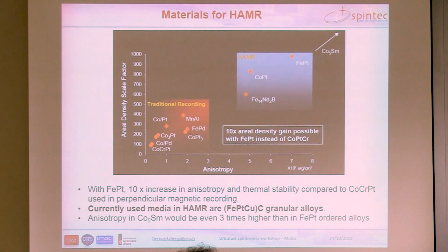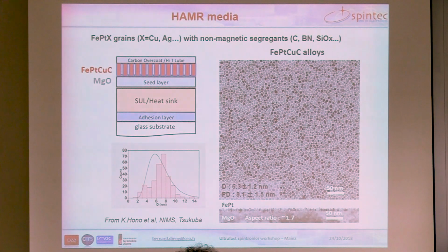So in this approach, we can use much higher anisotropy material, in particular iron platinum. The media currently used in HAMR are iron platinum copper alloys with carbon grain boundaries. Why copper here? To lower the Curie temperature of iron platinum, because otherwise the Curie temperature would be in the range of 600 degrees C, and there is a lubricant, a polymer, on the surface of the disc, which helps the sliding of the head, and this lubricant would not withstand such high temperature. So with copper, we can reduce the Curie temperature to around 400 degrees C, and then the lubricant can withstand this kind of temperature. Also the heating that we need is thereby minimized.